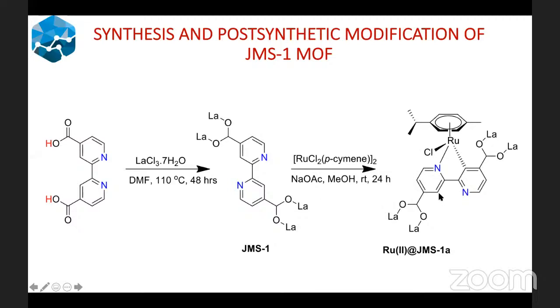And one would ask, why not that site also? This will depend on the size of the pores that are present in your MOF. If there is enough space, it means you can also have your ruthenium complex on that side of your MOF. But of course, if you also want to do that, you can introduce mesoporosity in your MOF. There are several techniques of doing that. Once you introduce mesoporosity, it means your MOF is able to accommodate bulky molecular complexes.